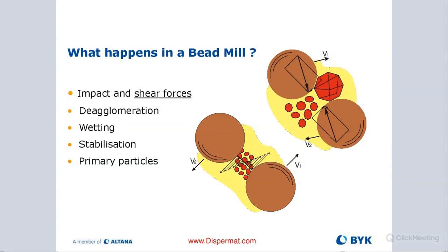So it's not that we're actually crushing our pigment particle, we're really just trying to break up the binding forces even when we are milling. The probability of a particle actually getting crushed is very small.